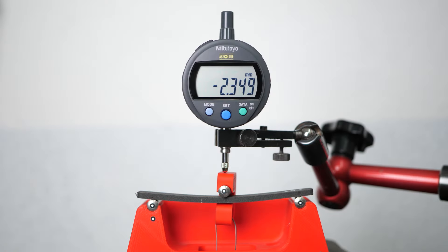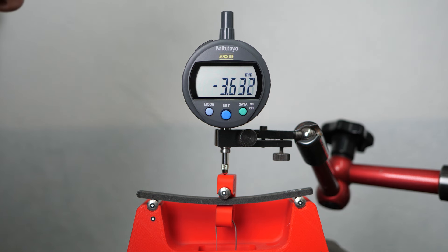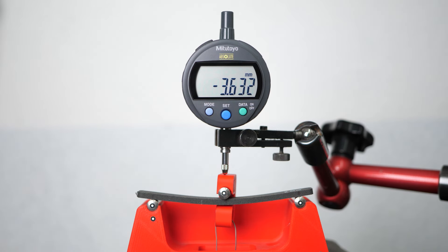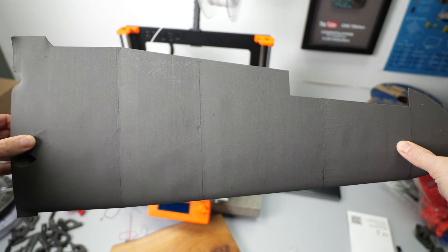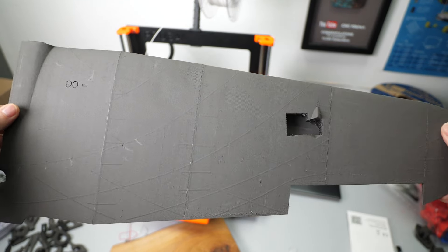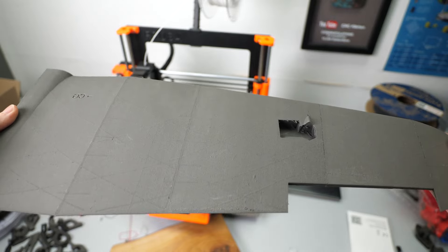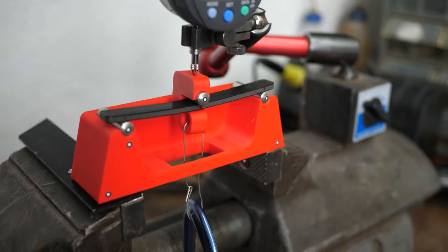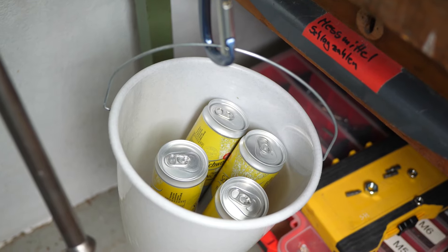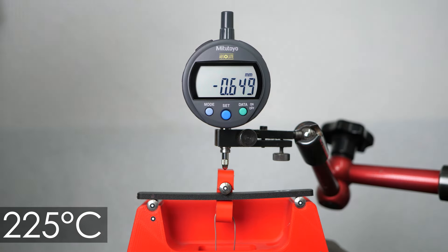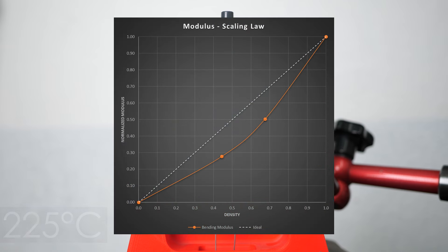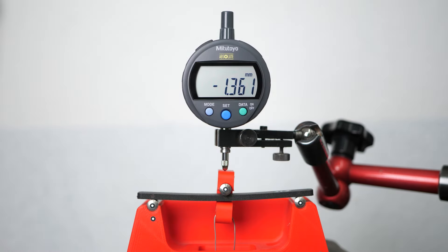Before we get to the impact test, let's take a look at the stiffness of the foaming PLA that I tested using a three-point bending test. This is a property that might be important for you if you are designing your plane for example so that the wings don't flex too much. The parts are placed in the jig and then loaded successively with weights while the deformation is recorded. The results are quite similar to the strength tests, meaning that the knockdown in stiffness is higher than the decrease in weight.